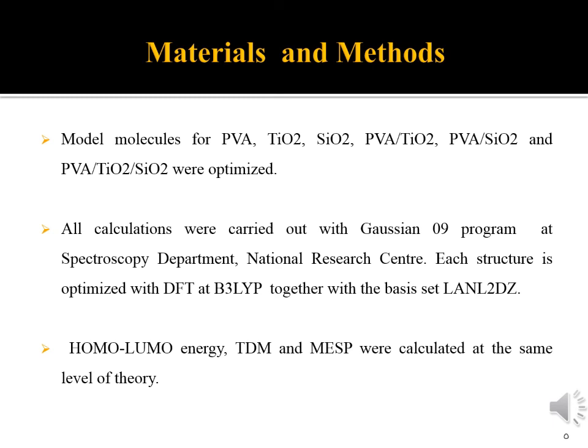Materials and methods. Model molecules for materials: polyvinyl alcohol, titanium dioxide, silicon dioxide, polyvinyl alcohol titanium dioxide, polyvinyl alcohol silicon dioxide, and polyvinyl alcohol titanium dioxide silicon dioxide were optimized. All calculations were carried out with Gaussian 09 program at Spectroscopy Department, National Research Center. Each structure is optimized with DFT at B3LYP together with the basis set LANL2DZ. HOMO-LUMO energy, total dipole moment, and molecular electrostatic potential were calculated at the same level of theory.